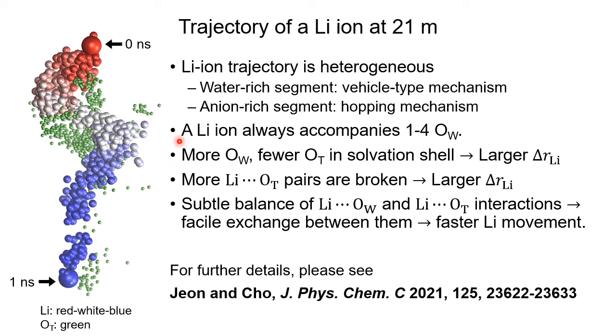And also, a lithium ion always accompanies 1 to 4 water-oxygen atoms, and if there are more water-oxygen and pure TFSI oxygen in the lithium-ion solvation shell, then that lithium ion will move faster. And also, if more lithium-OT pairs are broken in a given time span, that lithium ion will have a larger displacement in that time span. So combining all these, we can conclude that the subtle balance of lithium-OW and lithium-OT interactions enables this easy exchange of these two in the lithium-ion solvation shell, and it leads to faster lithium movement.